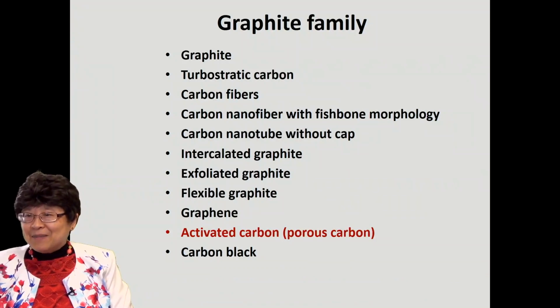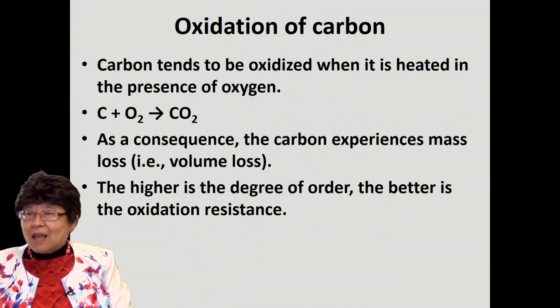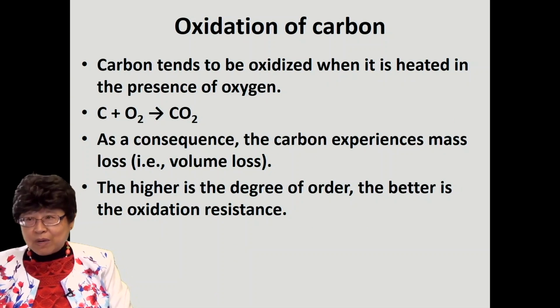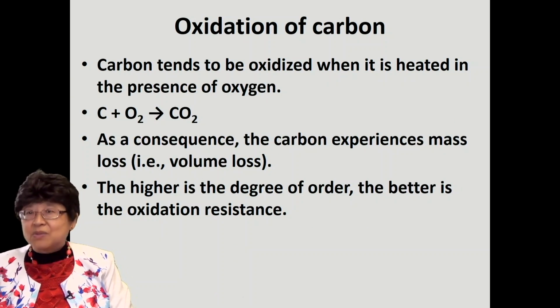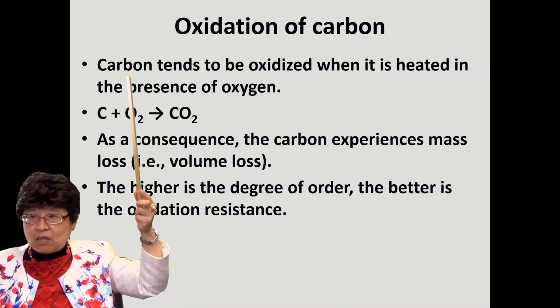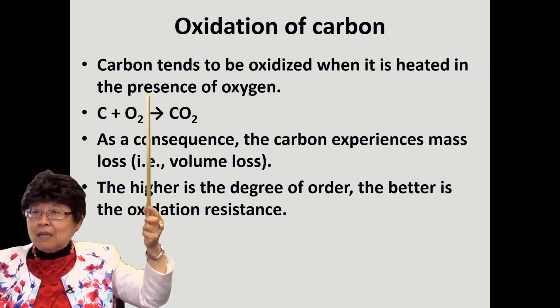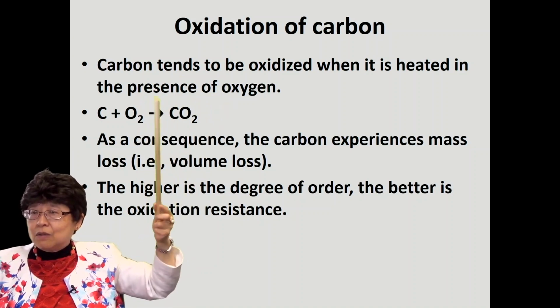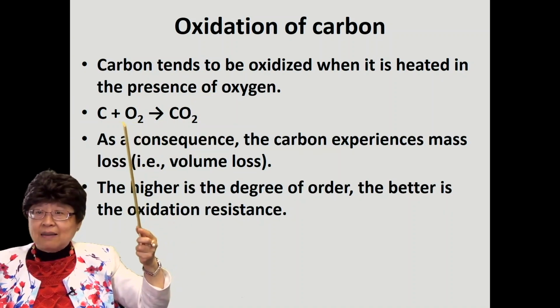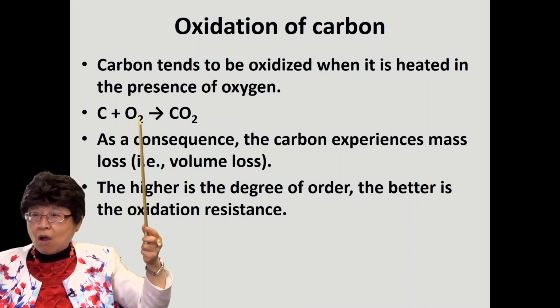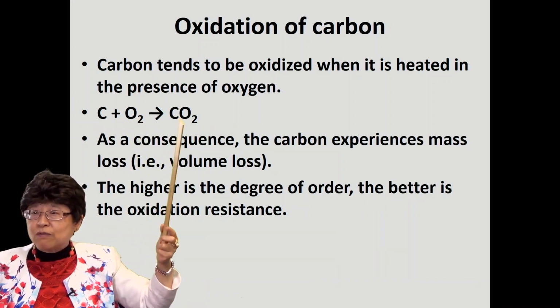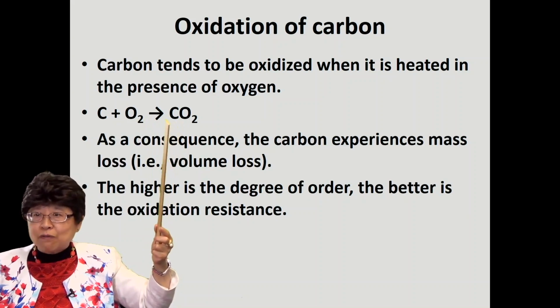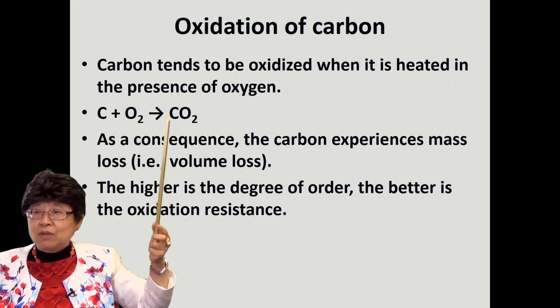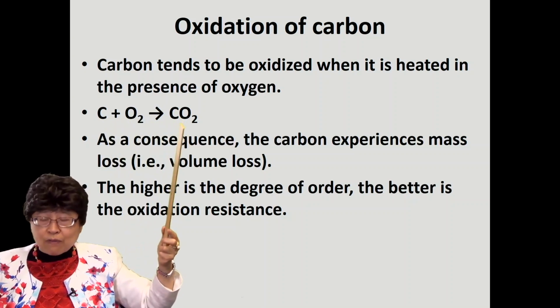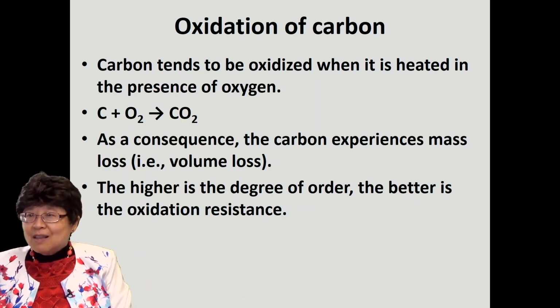Another is activated carbon. Activated carbon is porous carbon, but how do you make the pores or holes? That's made by oxidation of the carbon under heat. And this is one of the reactions that can be used for this purpose. You use oxygen, so this reaction forms CO2 gas, which comes off, and so the carbon is consumed by this reaction and becomes a gas which goes off, and so you get a hole, many holes. And you have mass loss as well as volume loss.